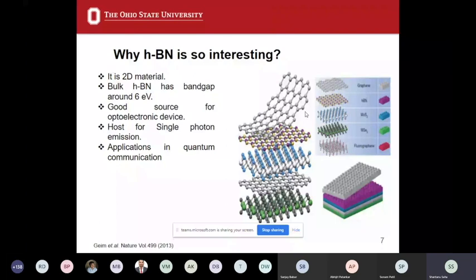And one of the most interesting features of hBN is that if you grow only one monolayer of hBN, you will see it has a direct band gap. Keep growing the layers, and when you end up with bulk hBN and measure the band gap, you will find it is an indirect band gap. This indirect band gap has been found so far to be 6 electron volts. And this platform is excellent for getting single photon emission.